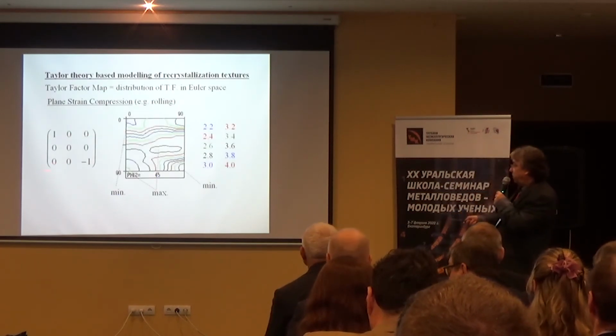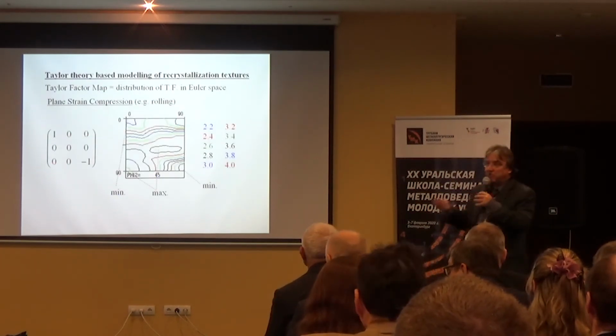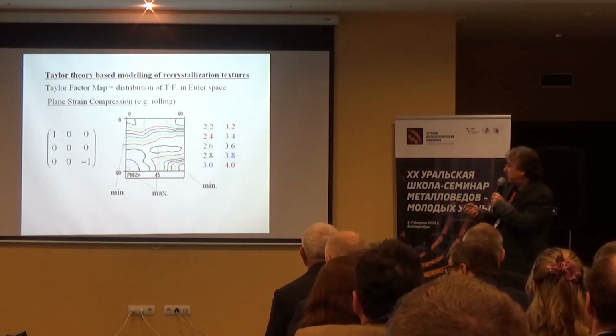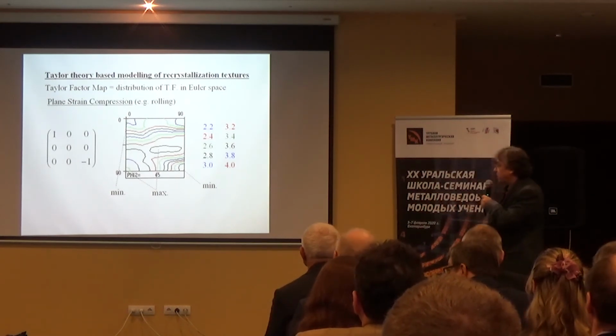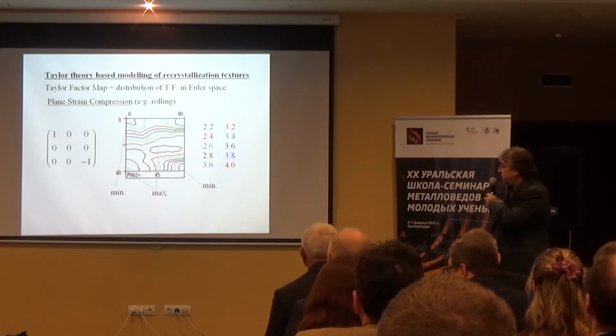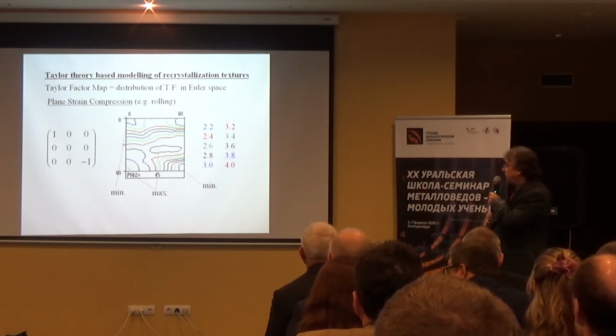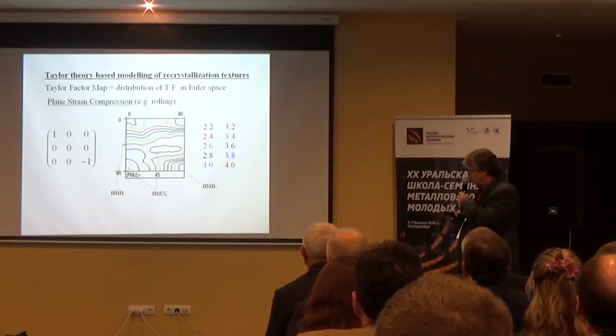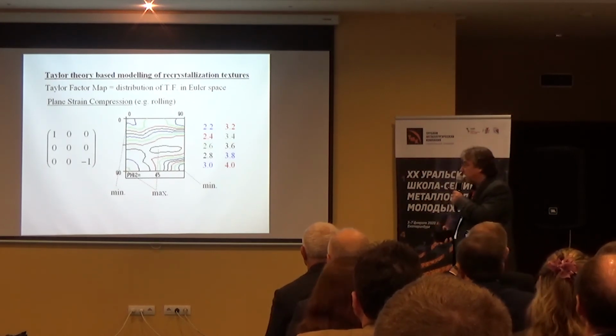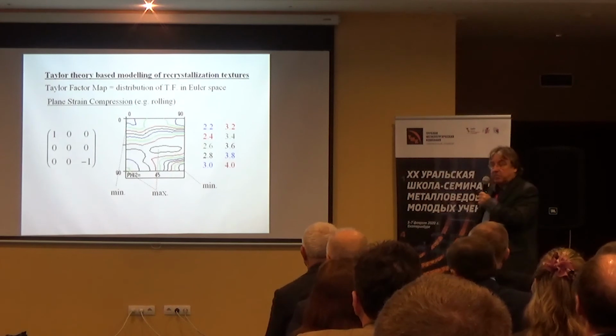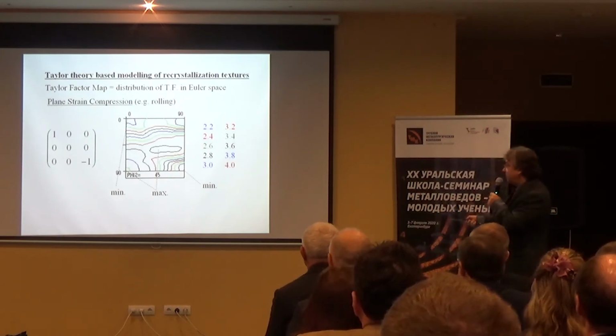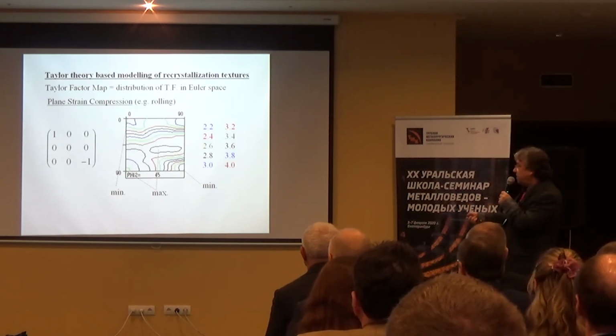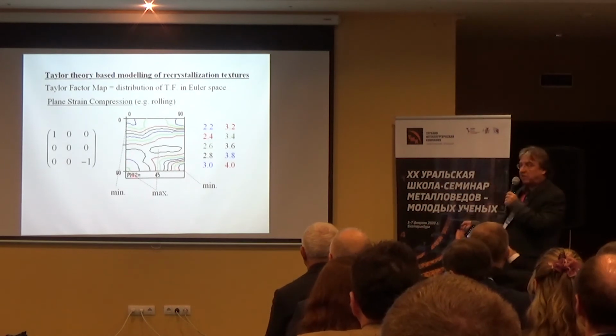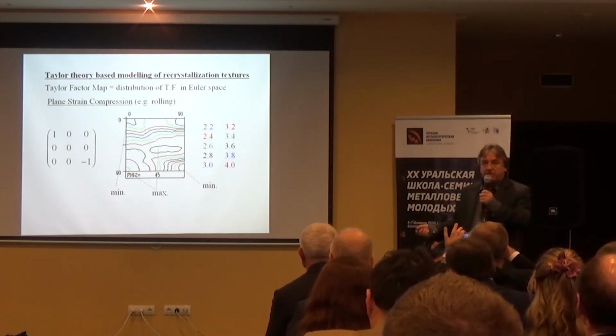For example, for plane strain compression, the example that I was showing, we have rolling. So this is the strain tensor, and to the right, what you see is a Taylor factor map. Sorry, it's not a texture map. This is not a texture. This gives you the distribution of the Taylor factor in the phi 2 45-degree section.